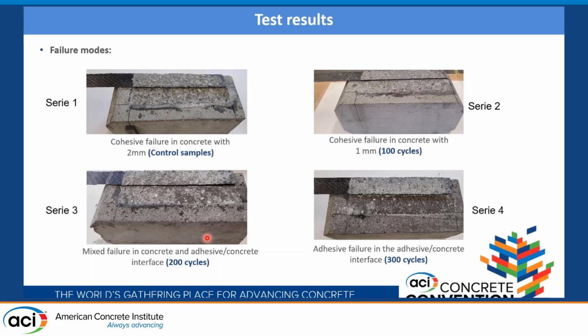Going now to present the experimental results. The mode of failure of the control samples, series 1, was a cohesive failure in the concrete substrate with approximately 2 millimeters of concrete remaining attached to the CFRP sheet. After 100 freeze-thaw cycles, series 2, cohesive failure in the concrete substrate was also observed, where a thin layer of 1 millimeter of concrete remained attached to the adhesive layer.